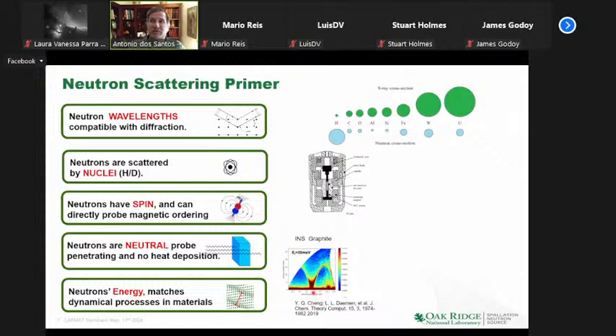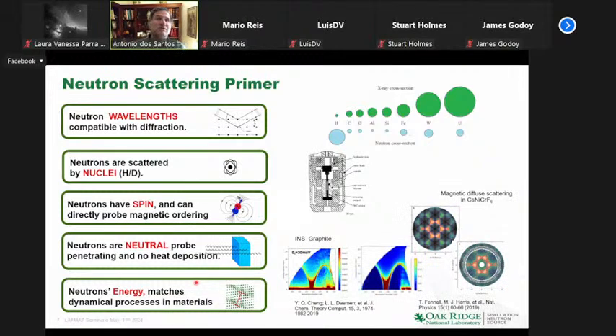So this is a case of a dispersion curve in graphite. Now, one thing that I don't say yet here on these images, but I will say now, is that neutrons are incredibly amenable to simulation. And this is because they're truly like a mass particle interacting with a lattice. So as you can see here, this is simulated data from this experimental graphite data, and you can see the detail. This is for inelastic.